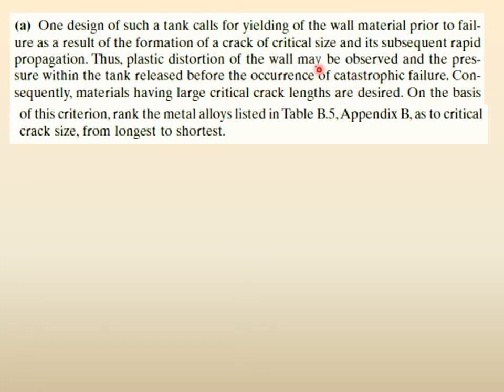So based on this, materials having large critical crack lengths are desired. Crack length, right? This is the critical crack length, not the current. There is some current crack length, but any material which will crack at a bigger length is good, and any material which will crack at a shorter length, critical crack. Therefore, you go to table B5, look at the different materials and find the critical crack size for each one of them. And then anyone which has a large critical crack size is good.